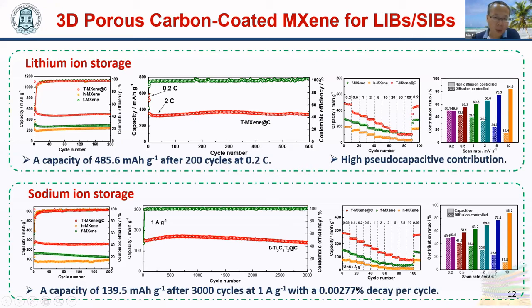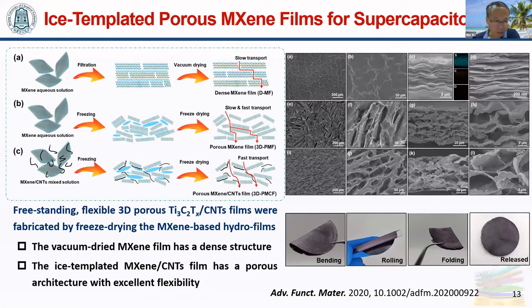We also prepared porous MXene films by ice template. The porous MXene films were prepared by freeze drying the MXene-based hydrogel films. The interior residual water during freeze drying was converted to small ice grains, which act as templates to create a porous structure. The introduction of carbon nanotubes in the interlayer increased the interlayer water and makes a more developed pore structure. Compared with the dense structure of the vacuum-dried MXene film, the ice-templated MXene film shows a porous structure. We can see many large pores. The film is freestanding and can be directly used as electrode material for supercapacitors.